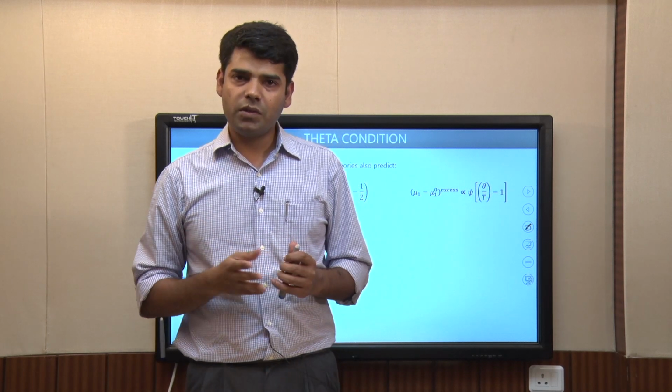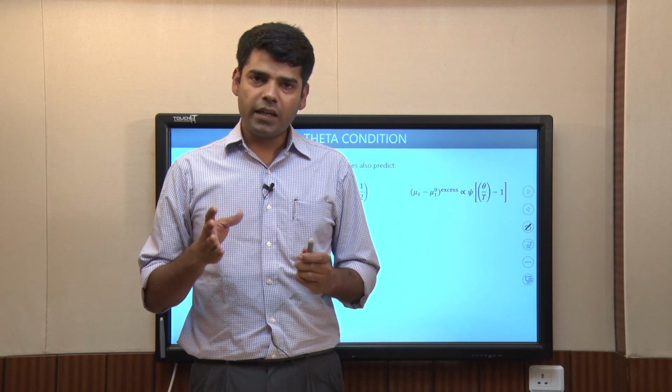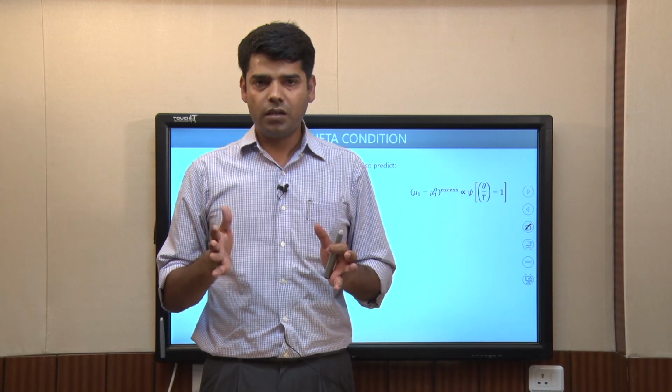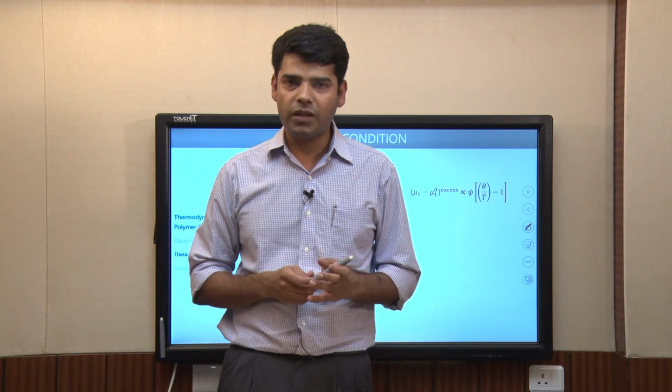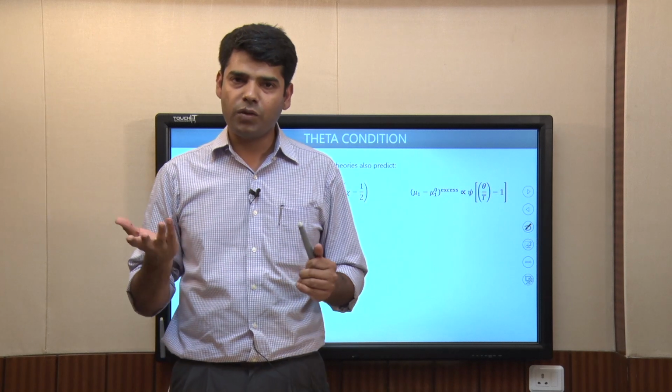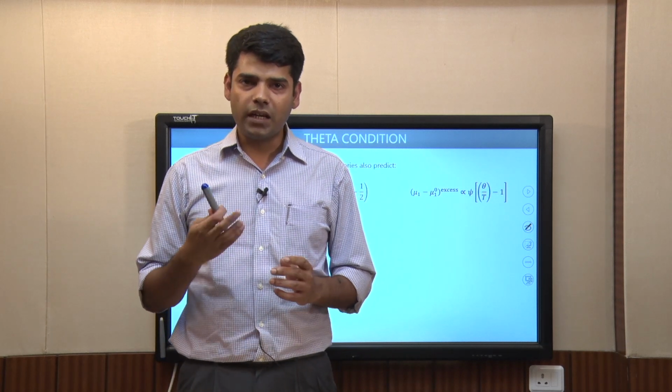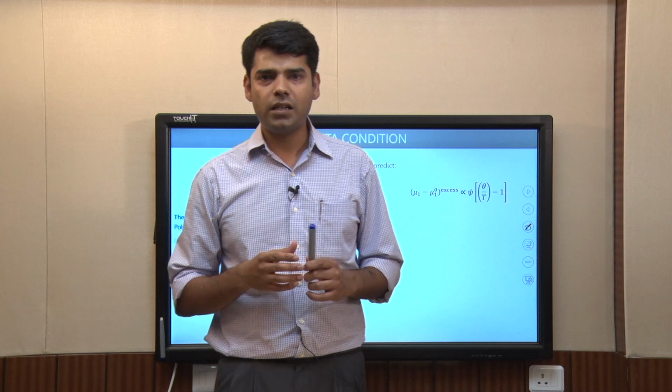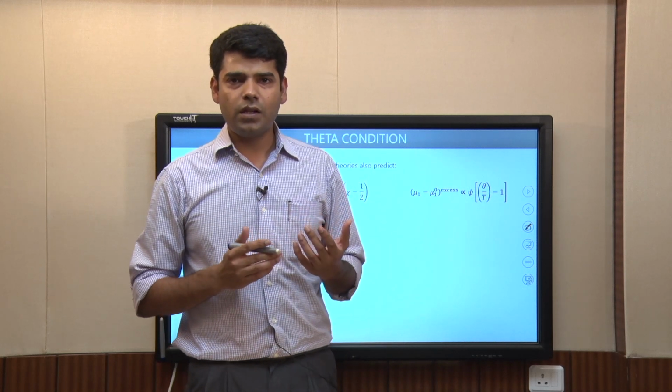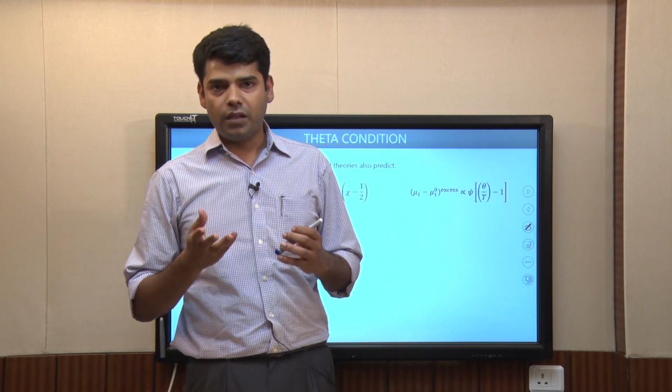Such a mean field approximation can only apply accurately to a system where the polymer segments are uniformly distributed, and that will correspond to a concentrated solution. So, that does not apply well to a dilute solution, and that is why it is said that Flory-Huggins theory is not a good theory to describe dilute